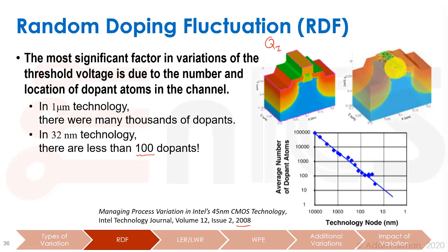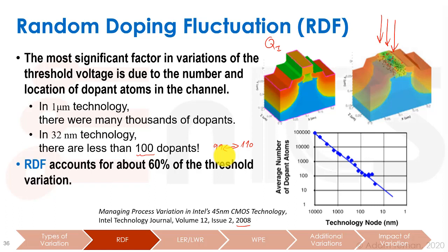We're shooting dopants at the channel with some flux for some amount of time, and statistically we expect, say, 100 dopants to be stuck in the channel. But what happens if 99 dopants are stuck in, or maybe 110? We're going to have real variation in the threshold voltage of our transistor, and that's a big problem. RDF accounts for about 60% of the threshold voltage variation of transistors. In many recent processes we've tried to go more intrinsic — having less implant inside the channel — in order to limit the spread of the threshold voltage variation.